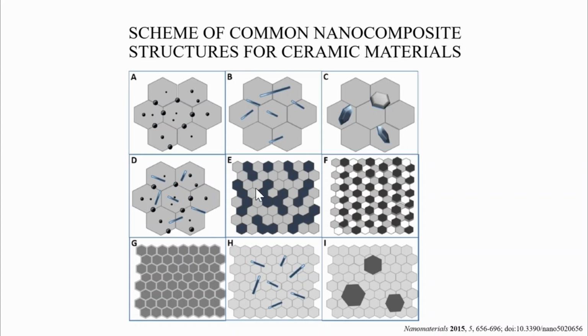Figure E showcases a nanocomposite structure composed of approximately equiaxed nanoscale grains of two distinct phases. These immiscible phases present in similar volume fractions form an interconnected structure where each phase impedes the growth of the other, limiting long-range interdiffusion. This concept extends to three or multiphase systems as illustrated in figure F. Increasing the number of immiscible phases also increases the diffusion distance between homologous grains, further refining the composite microstructure.